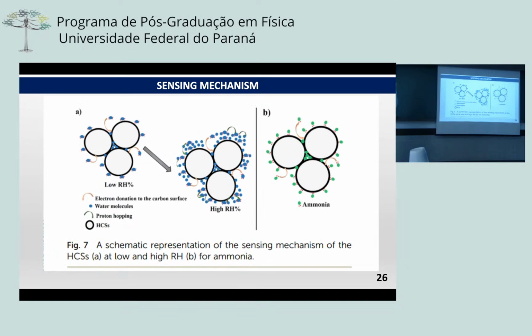So looking into the mechanism for sensing, these are hollow carbon spheres. They are not very electrically conductive. So the question was, where is the mechanism for this material? Because it's not electrically conductive. And after a series of discussions, we came up with the sensing mechanism, which is the pore filling mechanism, because it's a porous structure with pores on the shell, and the empty hollow sphere.